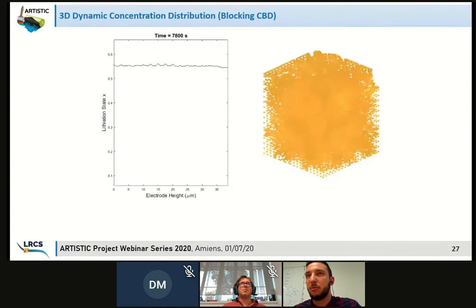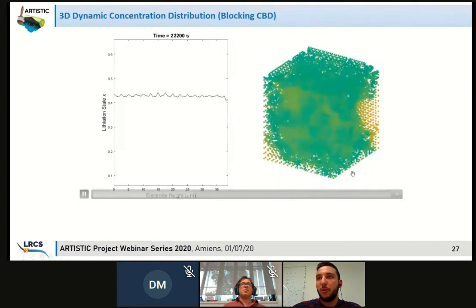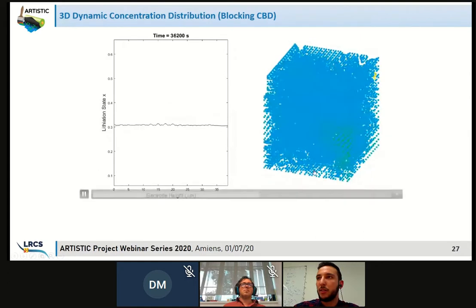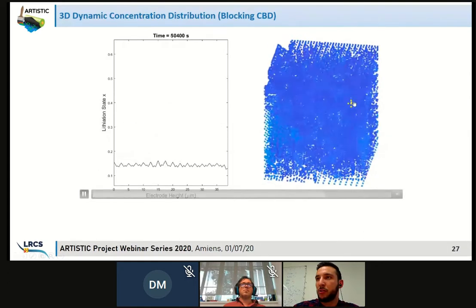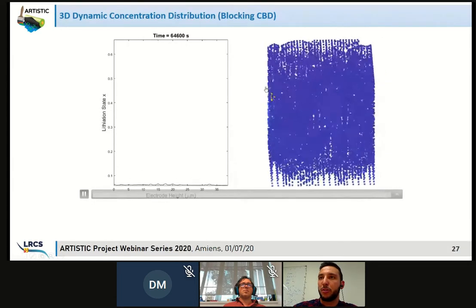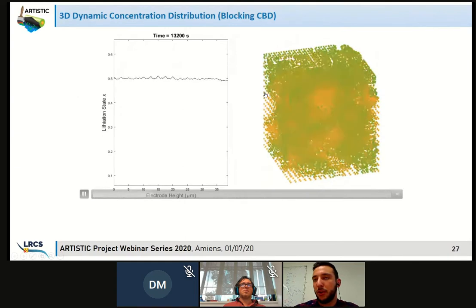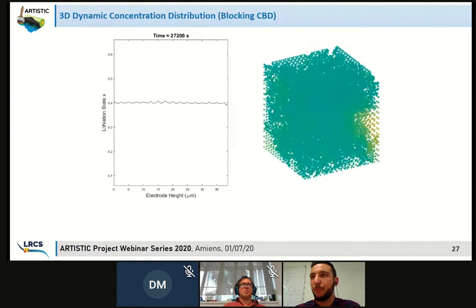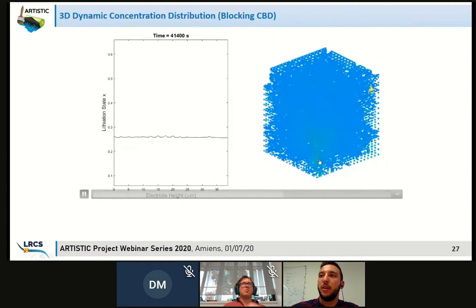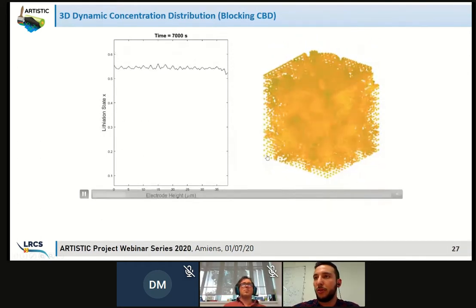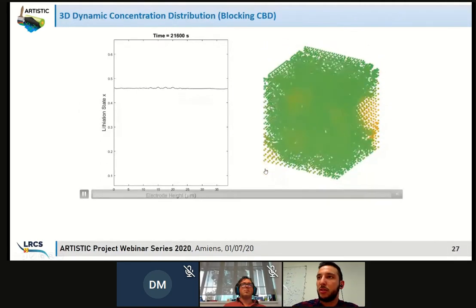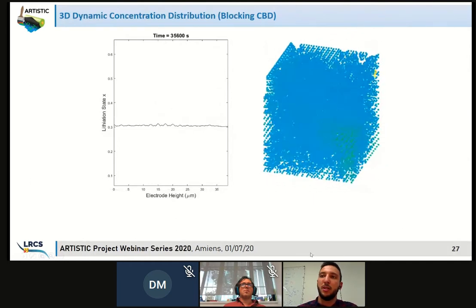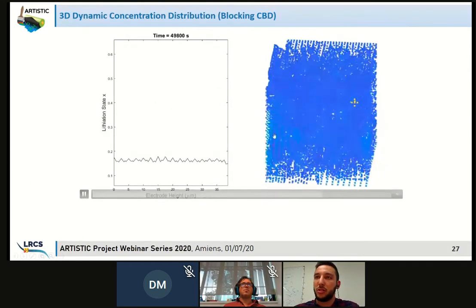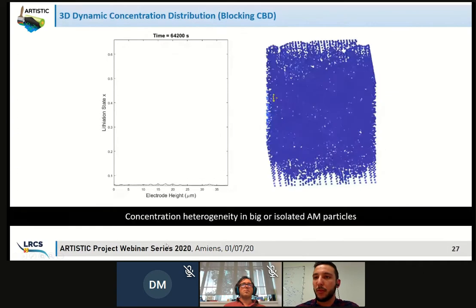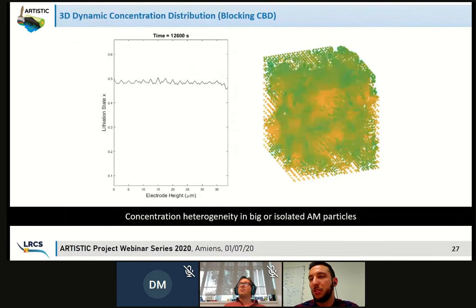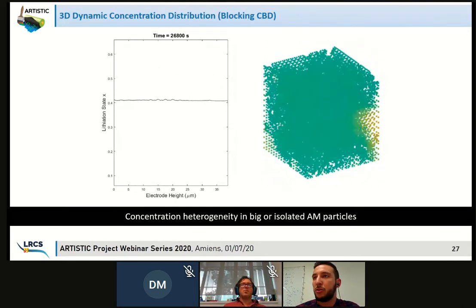You can also visualize it maybe a bit better in video. Right here you have this concentration plotted. And as you can see, there is a yellow isolated point here, which is due to an active material particle being isolated, prevented. There were no lithium ions that could go through. And then you can also see here, maybe I will show at the beginning, it's more clear. Then you have stronger gradients in bigger particles. Here, for instance, you can see it takes more time. You can see that it's not homogeneous, the concentration inside these big particles. So here, there is a heterogeneity due to these big active material particles or due to isolated ones.